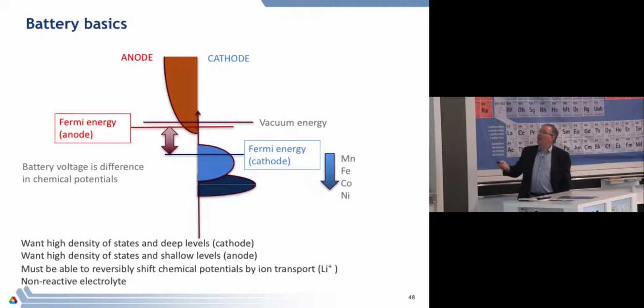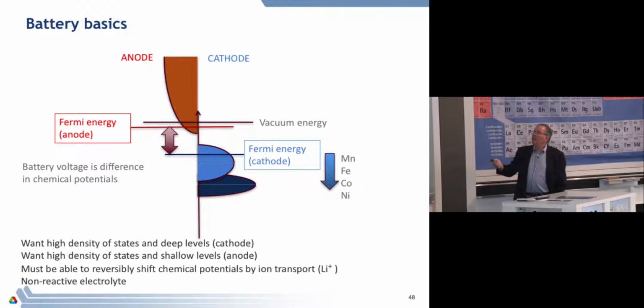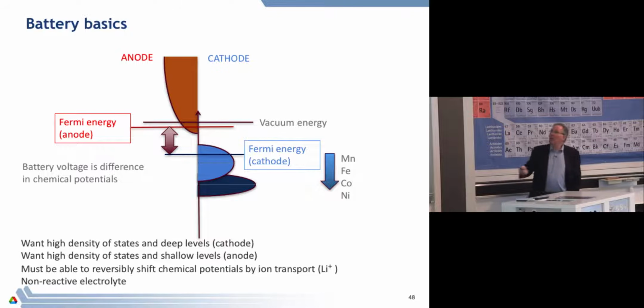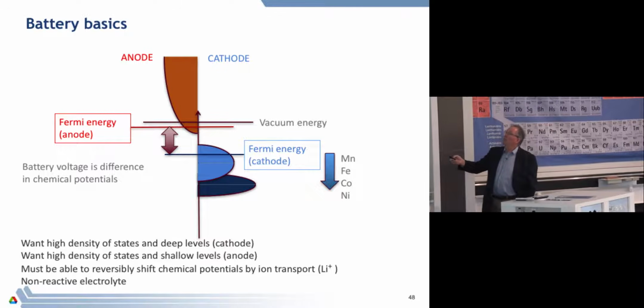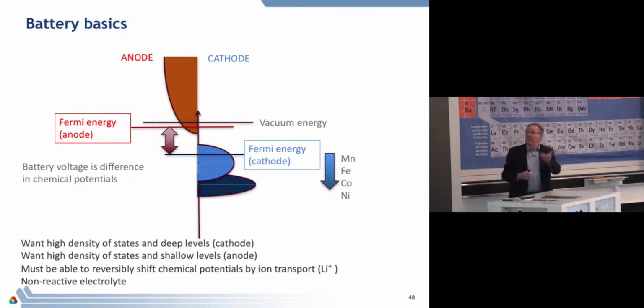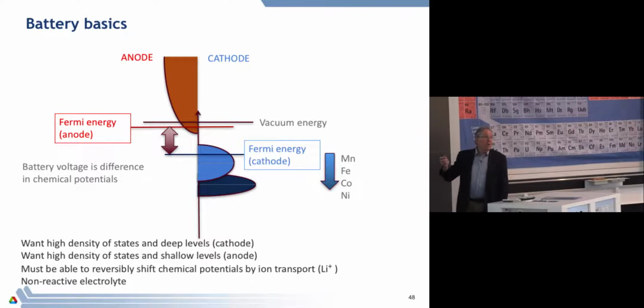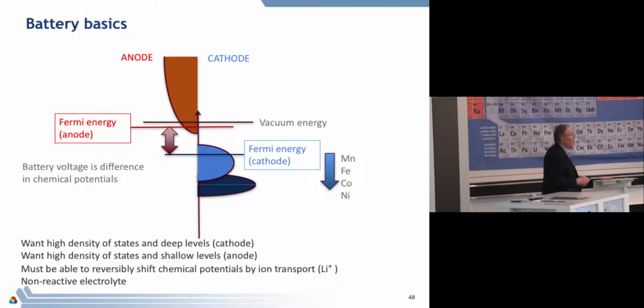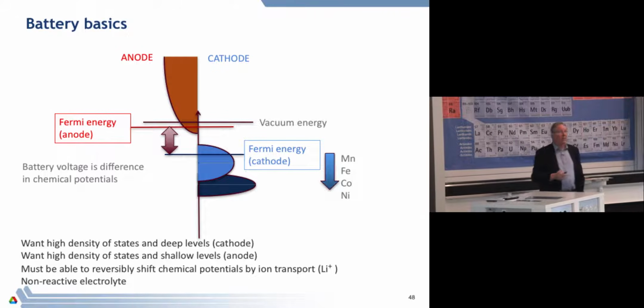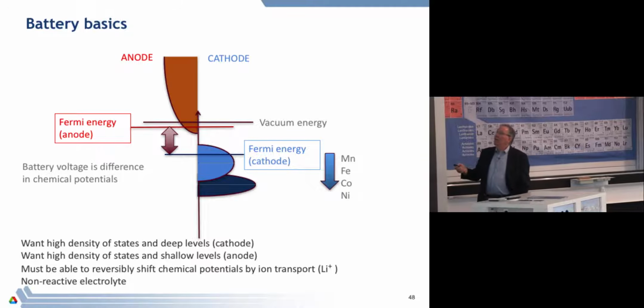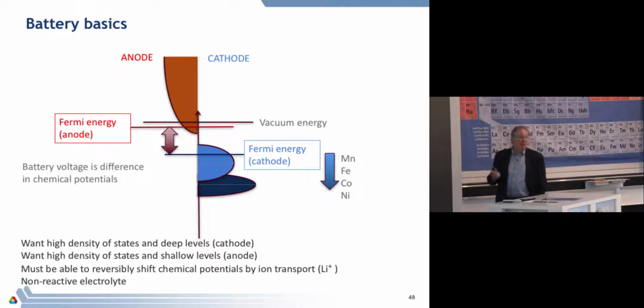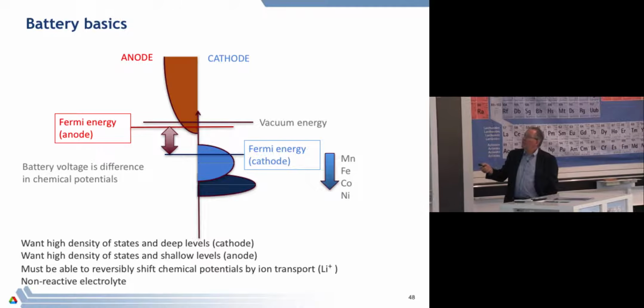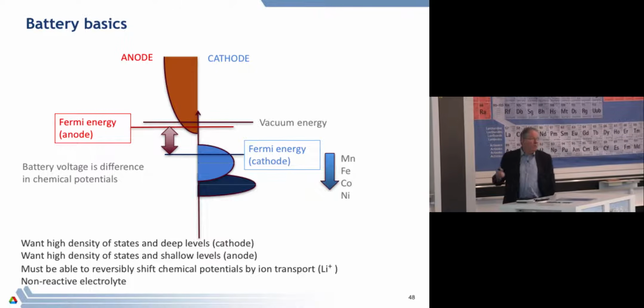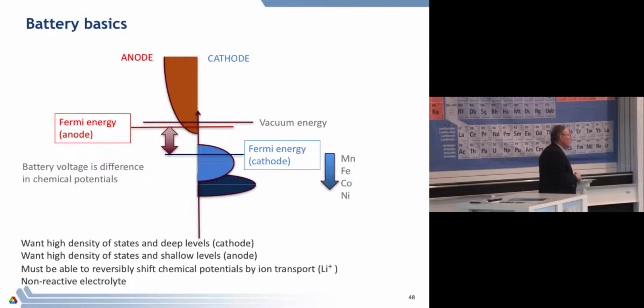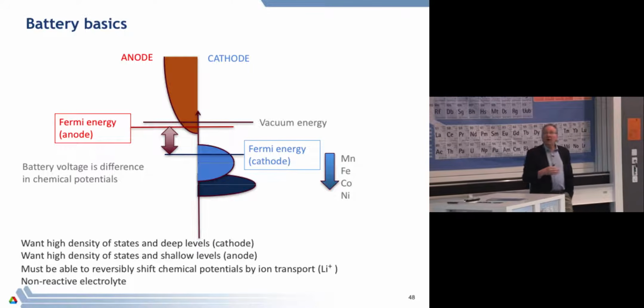Similarly, you'd like to get a high density of states with the anode, but that's tough to do because, of course, you can't get the chemical potential on the anode side above the vacuum energy. So you want something which is very high in energy, but it can't be above the vacuum. So the natural thing is to work with elements like carbon, which is why there is graphite. But lithium, by the way, doesn't go very far into graphite. As I put more and more lithium in this, the chemical potential moves up, and the Fermi energy will hit the vacuum level at a doping of about 1/6.